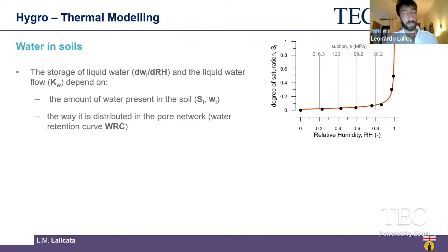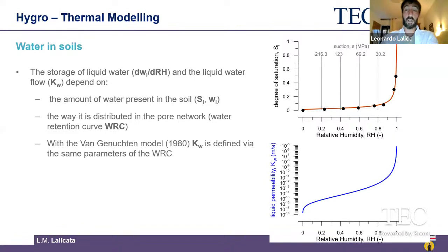The other good news of this modeling is that with the same parameters, in general, you can also model the evolution of the liquid permeability with the relative humidity or the degree of saturation. And what this equation tells us is that when the soil, our material, is fully saturated, the water can easily flow through the pores. This is because there is no air.